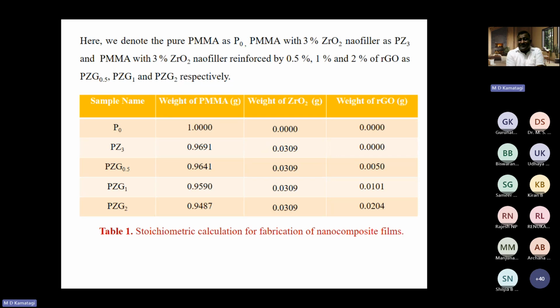We stick to 3% of ZrO2 because we knew that the higher ZrO2 reduces the mechanical strength of PMMA, and the 3 weight percent of ZrO2 increases the mechanical strength of PMMA. Therefore, we have kept it at 3%. And then we varied the weight percentage of reduced graphene oxide. So this is P naught, pure PMMA, where there is no ZrO2 or no RGO.